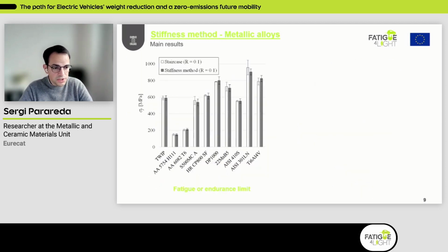So just to show a little bit the results that we obtained with this method, here you can see the results compared with the staircase method. So the fatigue limit at 2 million cycles obtained by the staircase method, a well-known, conventional method, and then compared with the stiffness method results. So here you can see that the results are almost the same.